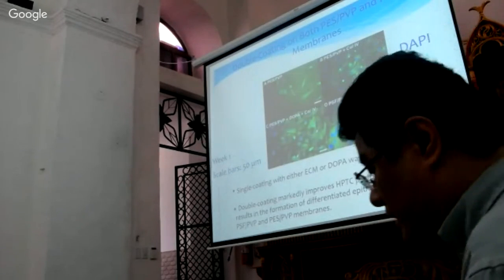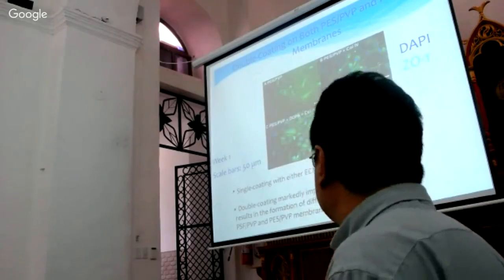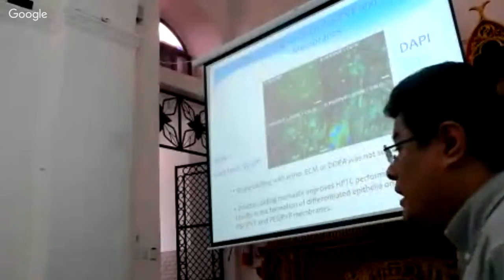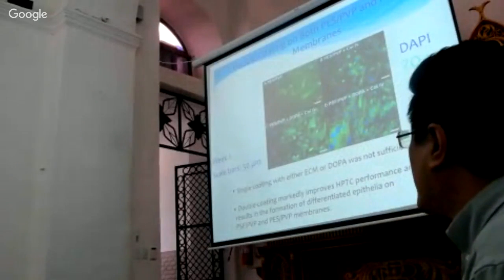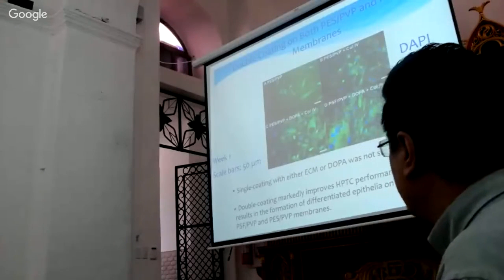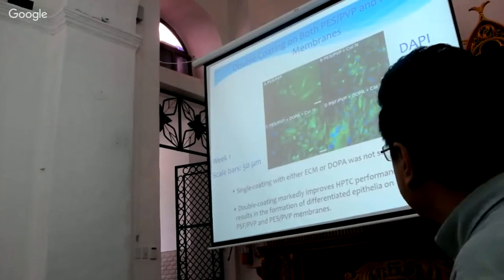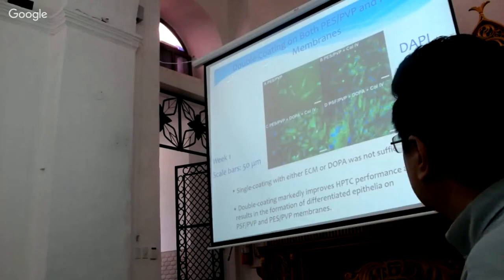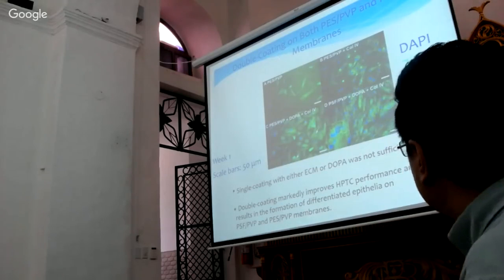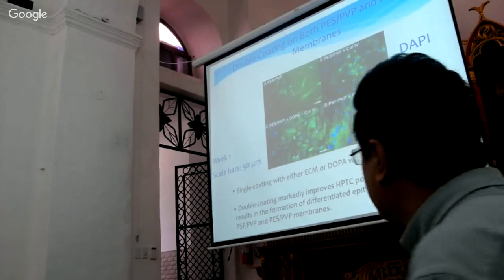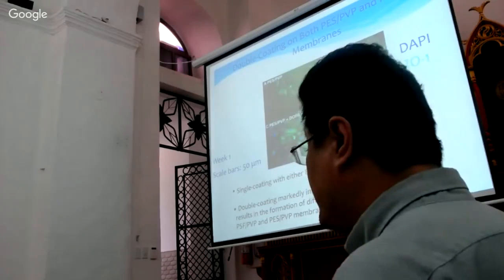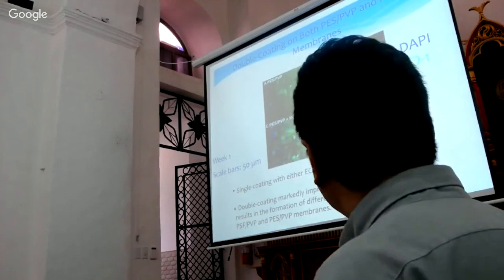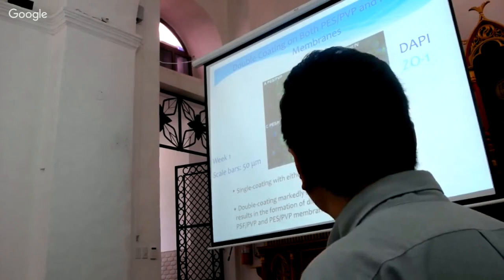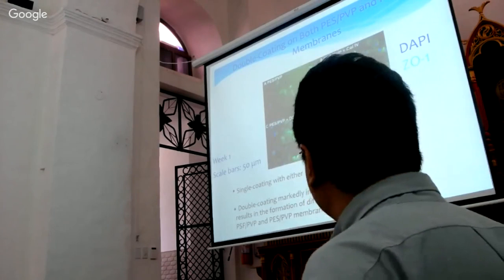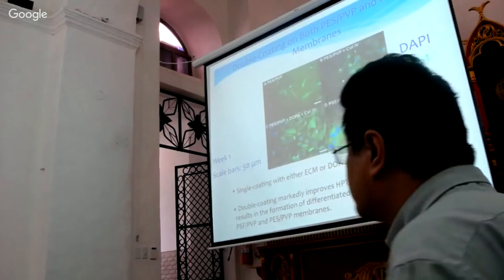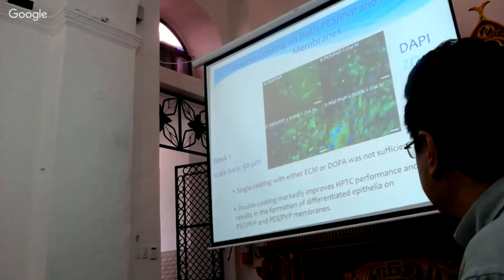So we found that simple ECM coating, extracellular matrix coating, doesn't work, really because they don't absorb well on the polysulfone, polyethersulfone membranes. How about we do this called double coating? So that means we first introduce DOPA coating on the surface. Since this layer is very sticky, and then we put ECM coating, in this case collagen 4. For that, we can really improve the performance of epithelial cells.